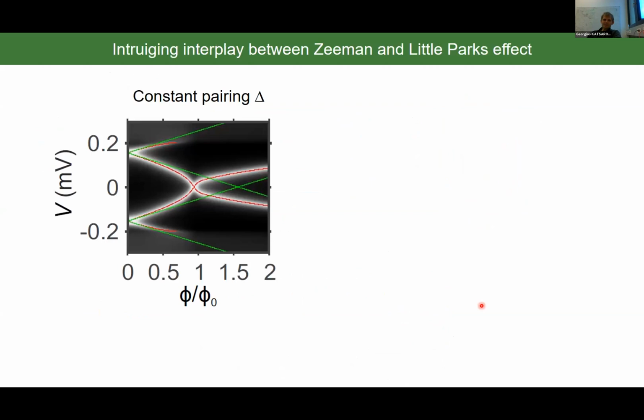So if you start with a superconducting Anderson model and you consider the constant pairing case, which is not our case, so that would be in some sense for a nanowire with a half shell, where when you sweep the magnetic field in a small range of magnetic fields, the gap is not modulated very much. What you can see here is the numerical density of states. So these are the Andreev bound states. The green lines would be the pure Zeeman evolution. And what you see in red are the poles of the Green function for the superconducting Anderson model.